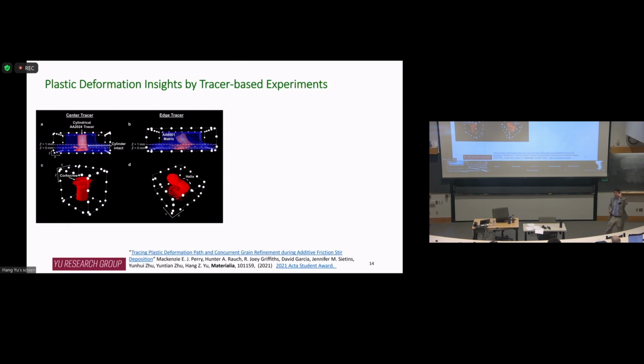Okay. So our feedstock is a rod, right? Now we don't use a homogeneous material. We use an engineered feedstock. So we have a rod. The base material is aluminum alloy 6061, which is an aluminum-magnesium-silicon-based alloy. We can drill a hole in the center. We put another aluminum alloy, 2024, inside there, right? So 2024 is an aluminum-copper alloy.